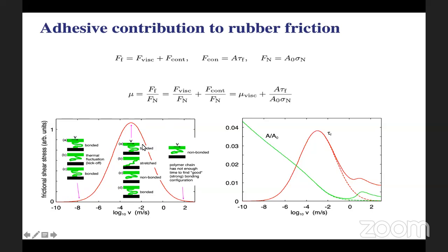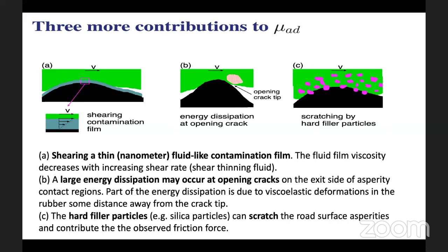So the fundamental here is that the chains bind to the substrate, and when they start, they perform stick-slip type of motion, releasing energy which contributes to adhesive friction. There are many more contributions to the adhesive friction coefficient, and this happens at the area of real contact.